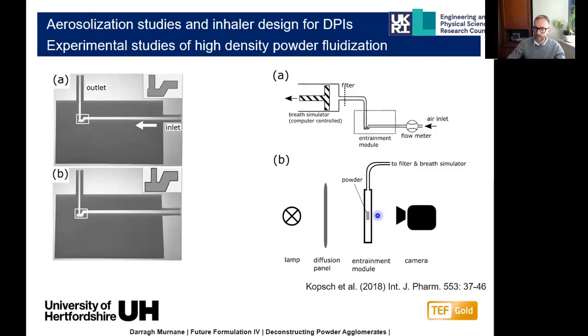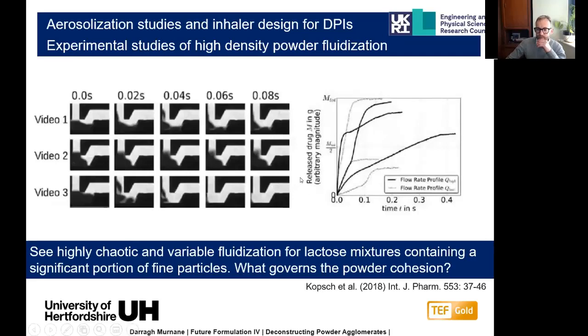And the whole time we study this using high-speed videography, and we're able to build up a model of the powder emission. And when we do that, we saw some pretty good fits with the bulk diluent lactose. But when we started to bring in materials which were much more representative of inhalation formulations, where there's a component of fine particles, in this case a material called Lactohale 200 that has roughly 20% of particles below about 30 microns or so,